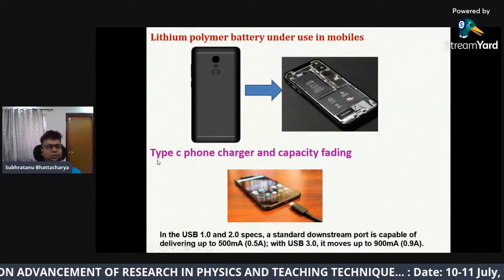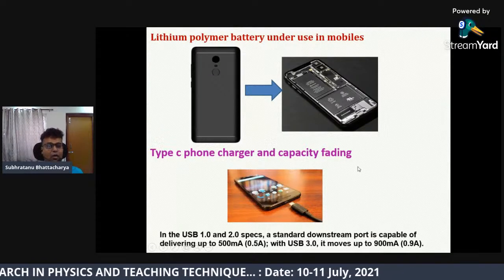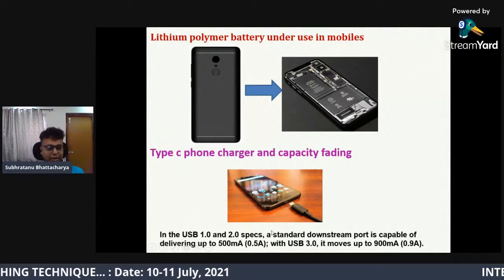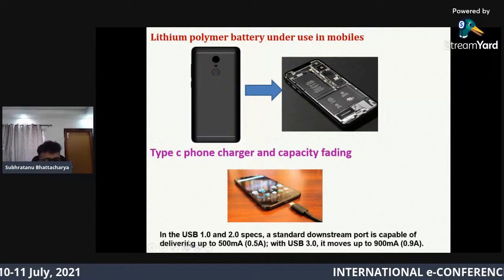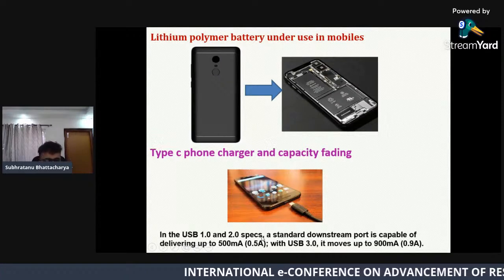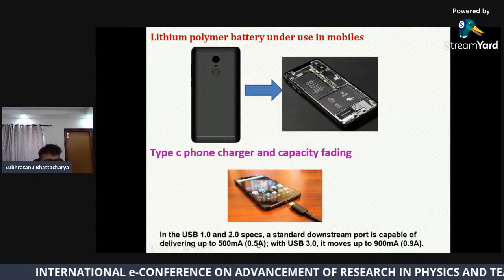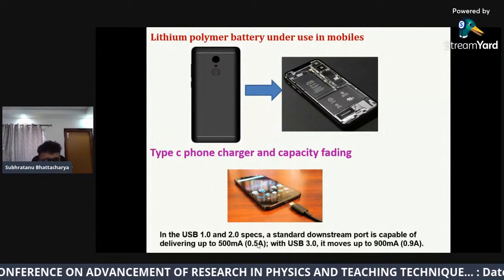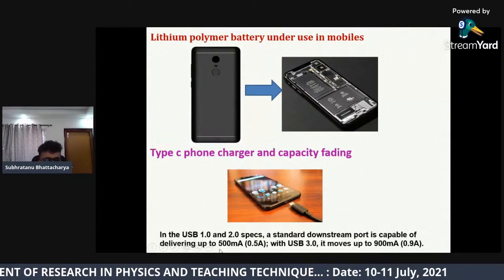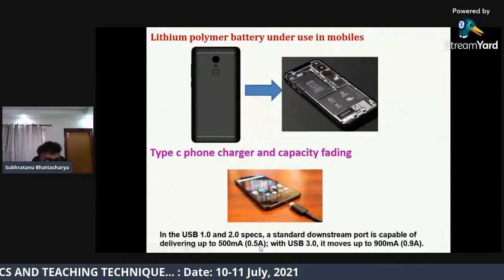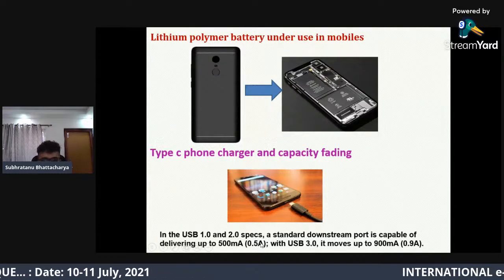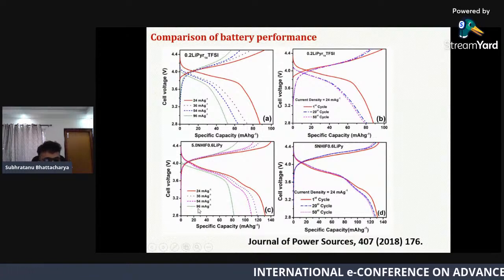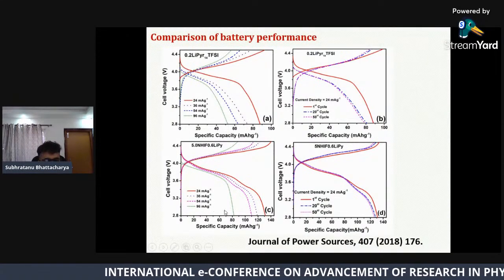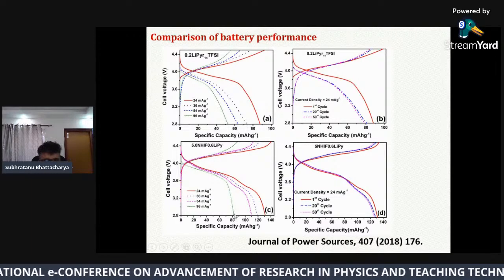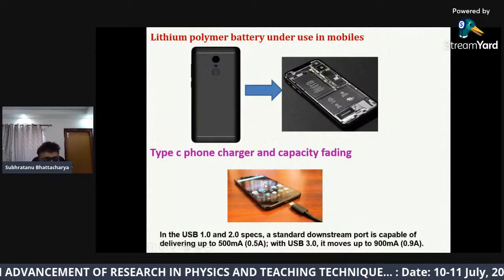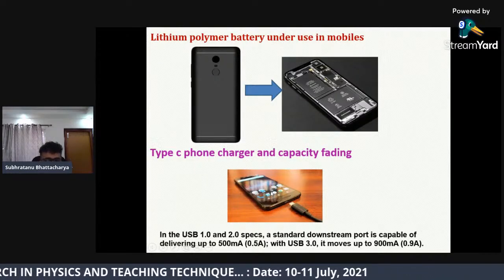Usually you use a Type C phone charger and capacity fading occurs. So what happens in this Type C charger, just for information: in the USB 1.0 and 2.0 specs, which are normally used in slightly older versions of these chargers, the standard downstream port is capable of delivering up to 500 milliampere, that is 0.5 ampere, during charging. And even at 96 mA per gram, you can see how the capacity fading occurs. So you can understand what your battery is actually getting during this charging.